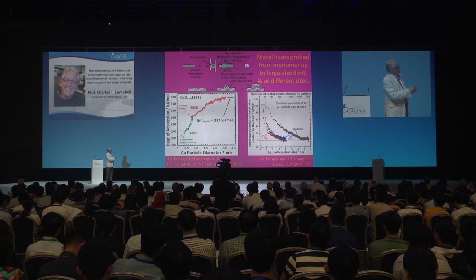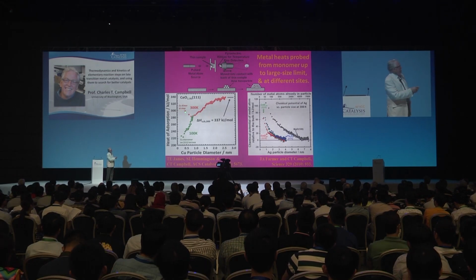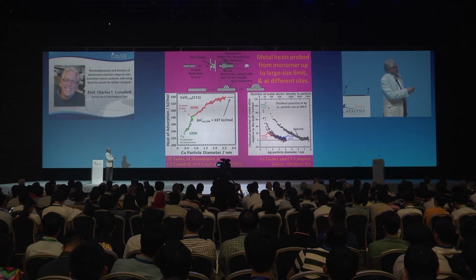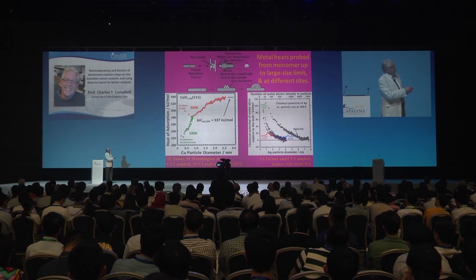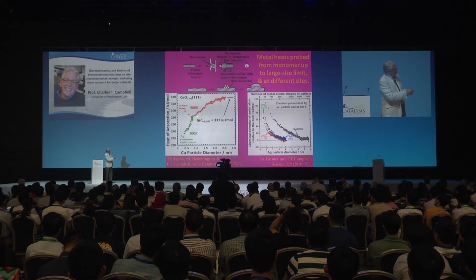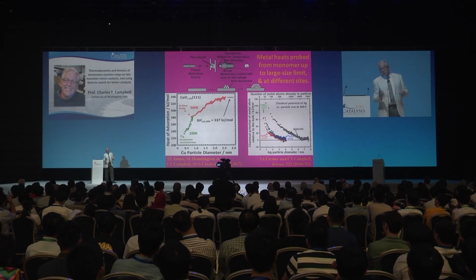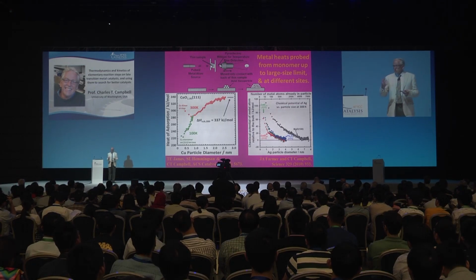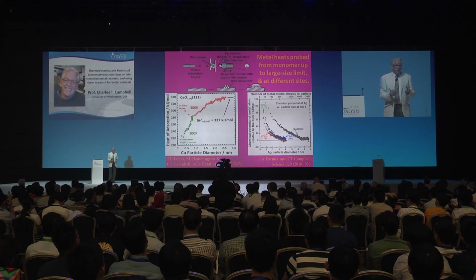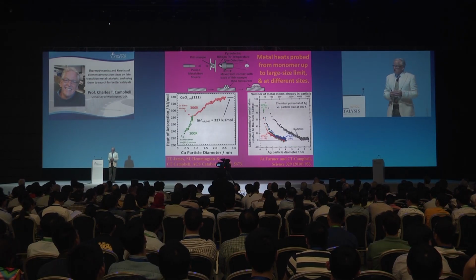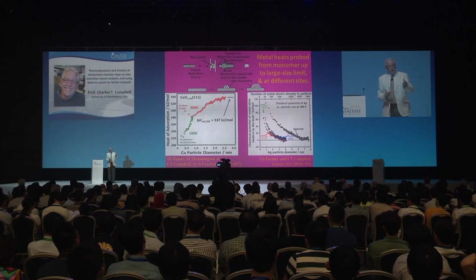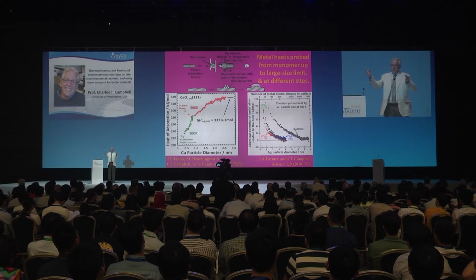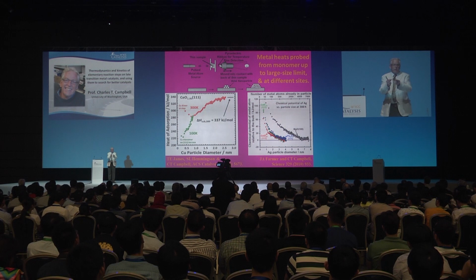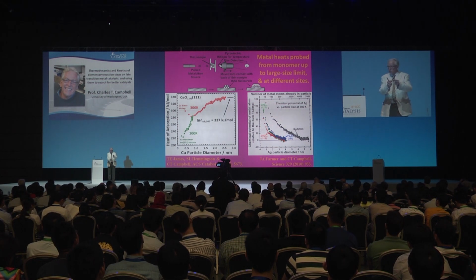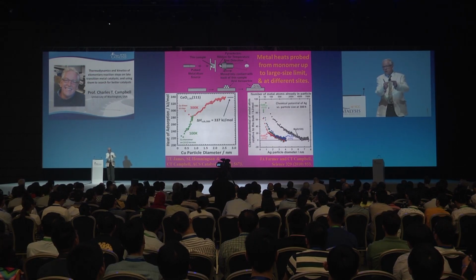At room temperature, you already make a dimer in the first pulse of gas, and as the step edges are titrated, the heat of adsorption decreases, and then it grows again. And this growth, the overall growth, is a very common result, that the heat of adsorption increases with particle size, and it can be understood very simply from the number of metal-metal bonds that are made. If you imagine that you have a dimer and you adsorb another metal atom to that, the most metal-metal bonds you can make are 2 to that new metal atom, plus it has a bond downward to the oxide below.